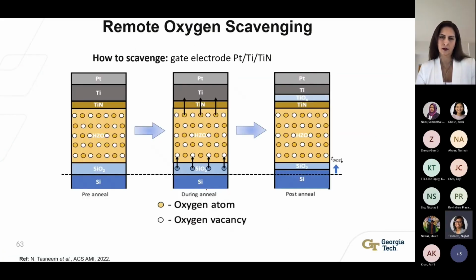So for my experiment, I used a remote oxygen scavenging technique to lower the interfacial layer thickness in the MFIS gate stack in an MFIS structure. So let's give a brief overview of the scavenging technique. In this case, we used a well-known method where a titanium nitride stack is used as the top gate electrode. And titanium is a very reactive material which can scavenge the oxygen from the silicon oxide interfacial layer through the titanium nitride layer. And thus, it can lower the interfacial layer thickness.